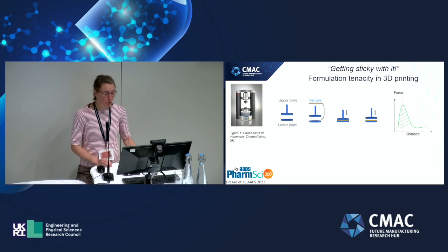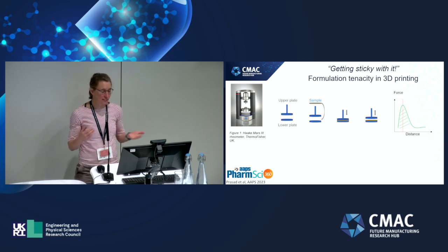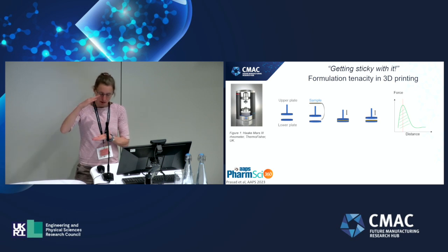So this is why it's important. So what we're doing is we're performing a tack test. We've got a sample sequence where we're introducing a sample to a parallel plate geometry that's preheated. We're lowering the top plate. They're in good contact with each other. Then we're removing the upper plate and we're measuring the force that's required